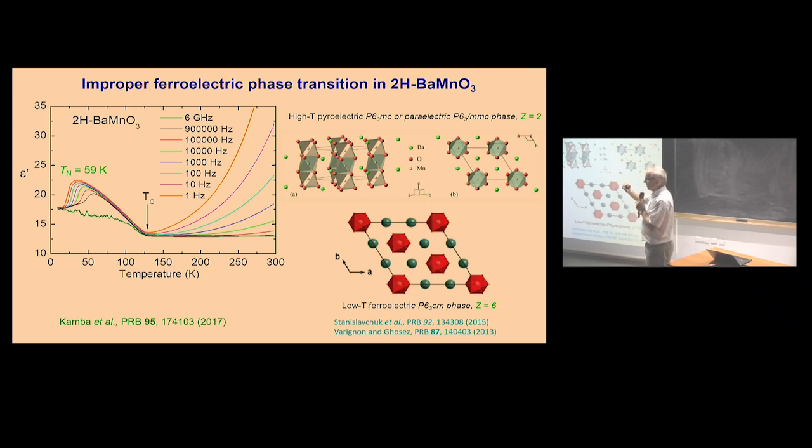You can have, let's say, a depletion layer close to the electrodes, which gives you a huge capacity because the depletion layer is very thin, and the rest of the bulk does not contribute to permittivity. So you can measure huge capacity, and it looks like you have giant permittivity, but it is just the so-called Maxwell-Wagner relaxation mechanism for the appearance of relaxation.